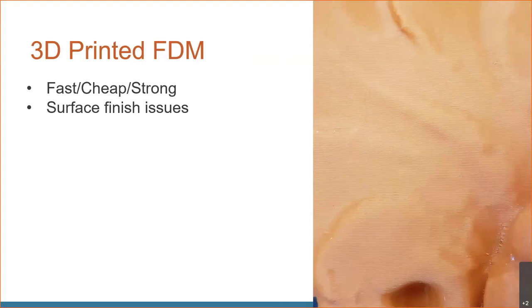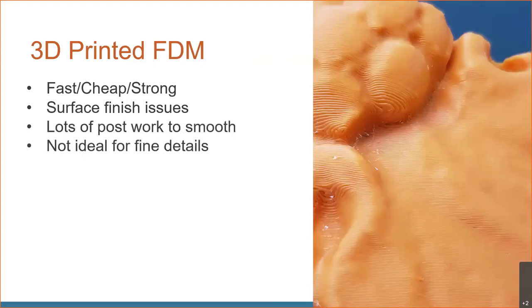Because this part has so many different features, curves, and geometries all over it, there's no single orientation that makes everything perfect. You'll always end up with more prominent layer lines and stepping in some areas — such as on the berries — which will require a lot of smoothing and detail work. FDM is also not great for very fine details, so depending on the architectural features being replicated, FDM could be lacking. This may rule it out depending on how much post-processing time you have available.